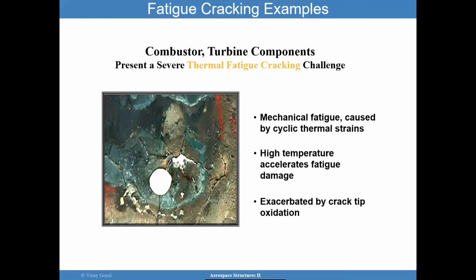Combustor, turbine components present a severe thermal fatigue cracking challenge. You have mechanical fatigue caused by cyclic thermal strains, high temperatures accelerating fatigue damage, and then you have oxidation at the crack tip that can make things worse.